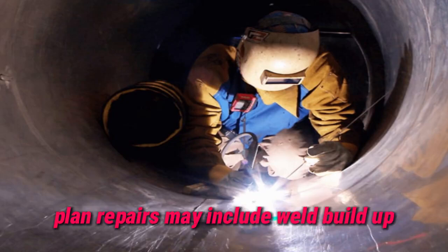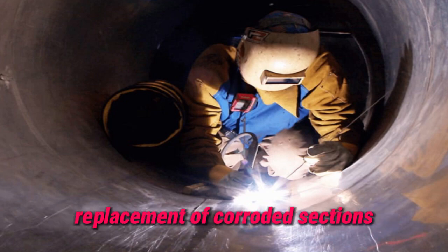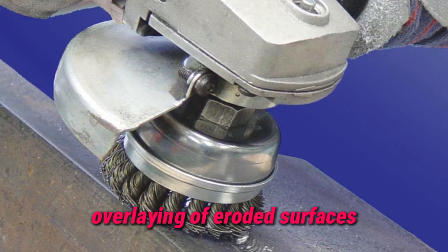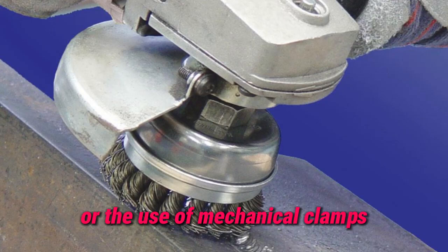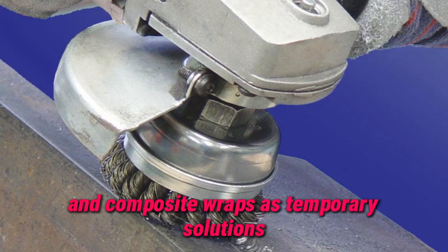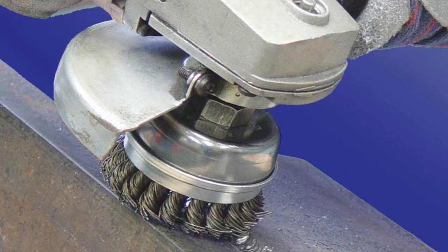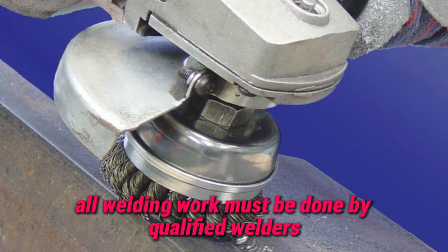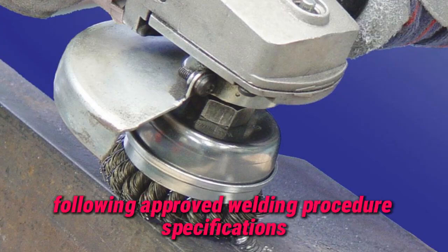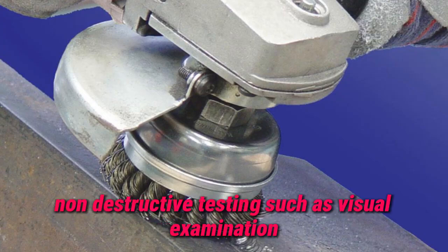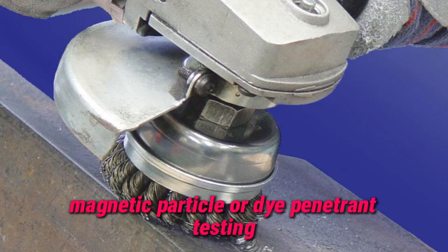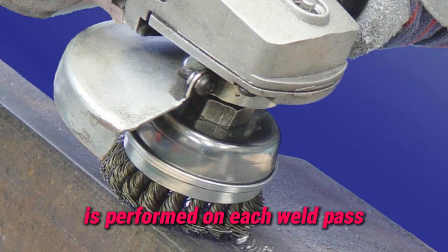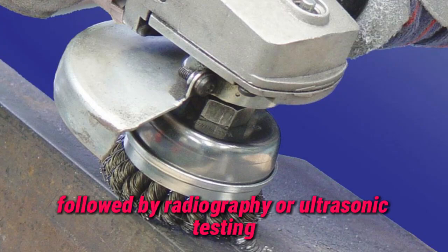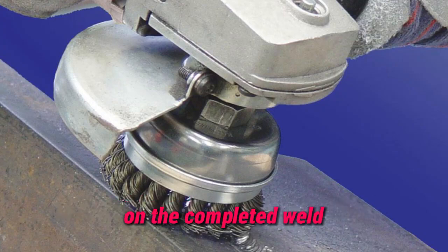Repairs may include weld buildup, replacement of corroded sections, installation of insert plates, overlaying of eroded surfaces, or the use of mechanical clamps and composite wraps as temporary solutions. All welding work must be done by qualified welders following approved welding procedure specifications. Non-destructive testing such as visual examination, magnetic particle, or dye penetrant testing is performed on each weld pass, followed by radiography or ultrasonic testing on the completed weld.